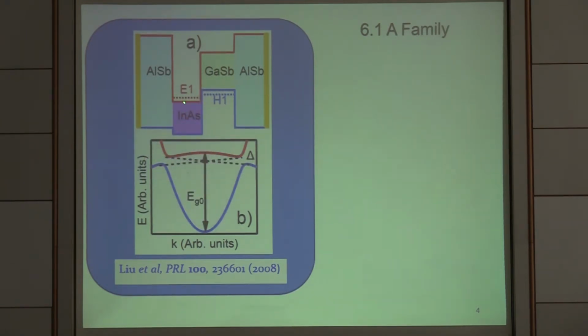If you group them together, then you have an inverted structure, as shown here: the ground state of the conduction band is lower than the ground state of the valence band. So if you allow these to tunnel with each other, then you have a hybridization-induced energy gap at some finite k, the kF point, kF and minus kF. So you open a small gap. This small gap is called a mini gap, on the order of 4 to 5 milli-eV in the usual parameter range. And then a Kramers pair will be generated and will propagate along the edge, along the perimeter of the sample, and this will be spin-momentum locked.